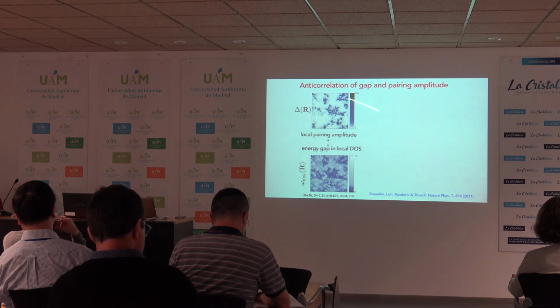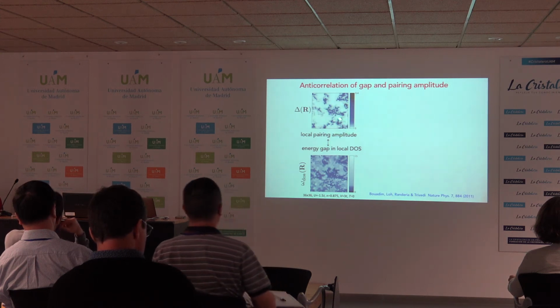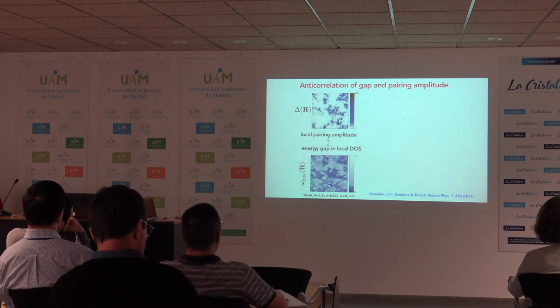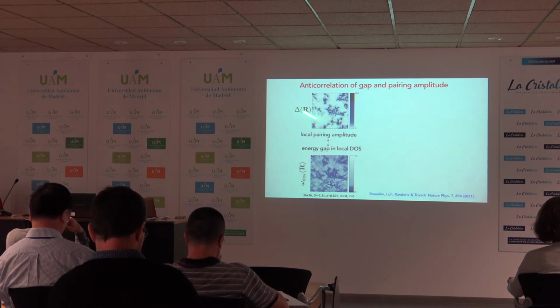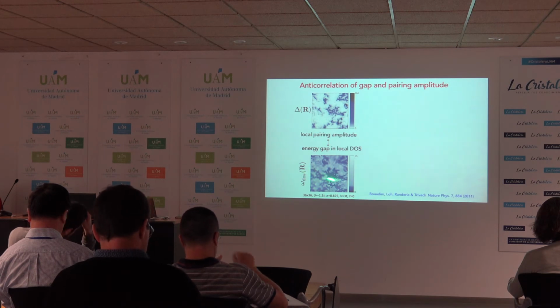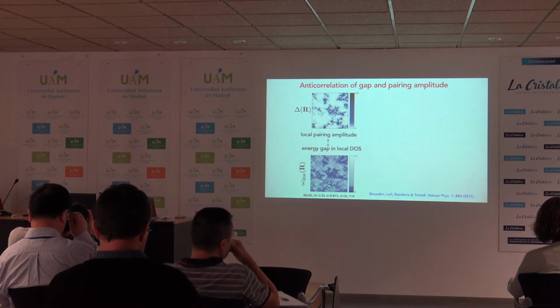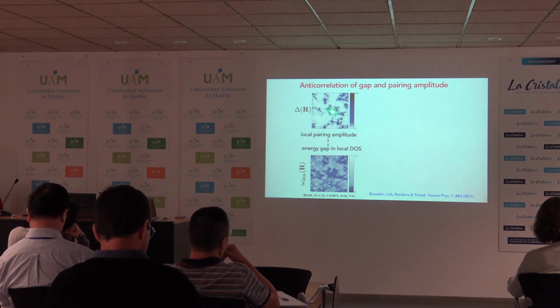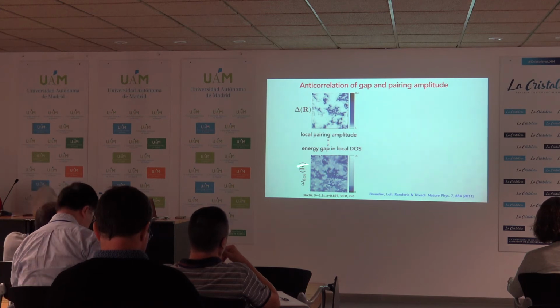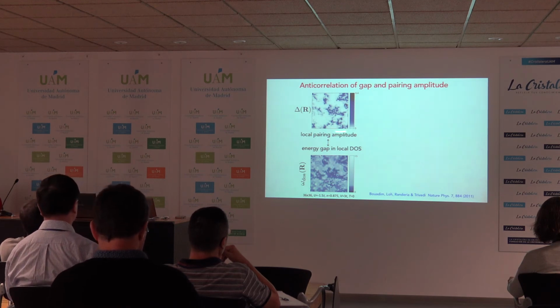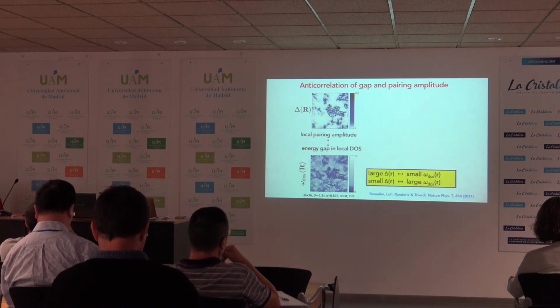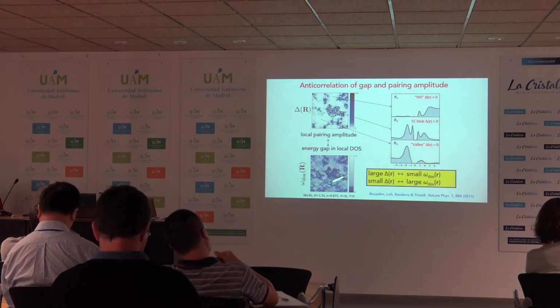So here's the evidence for that. This is from actually beyond even Bogoliubov-de Gennes. This is including the fluctuations. This is the local pairing amplitude map at some value of the disorder where you have these patches. And this is the local gap. So at each point I have taken that spectrum and extracted the gap, and I have inverted the scales. So here dark means large pairing amplitude, here dark means a small gap. So you can see that on the patch, the gaps are smaller. In the white regions, where there was no pairing, the gaps are larger. So this is the anti-correlation. And this is the actual spectrum in these different regions, and that's the result.